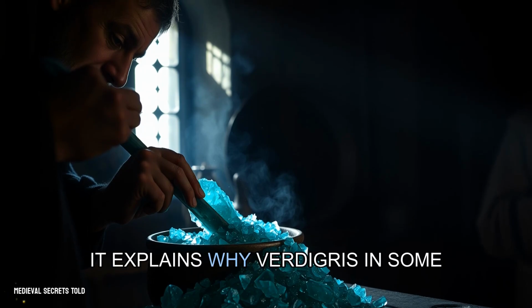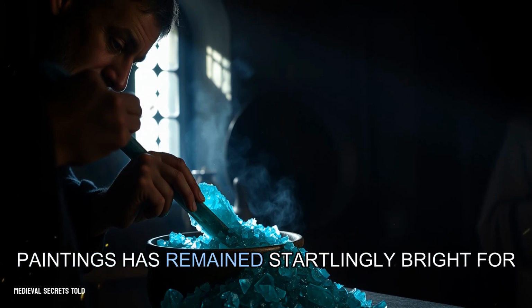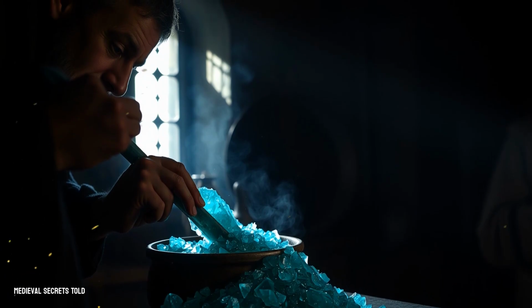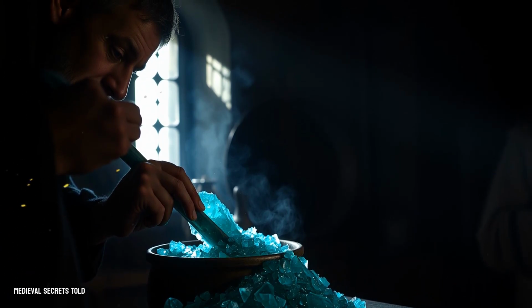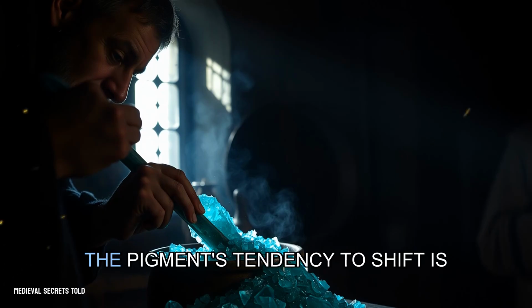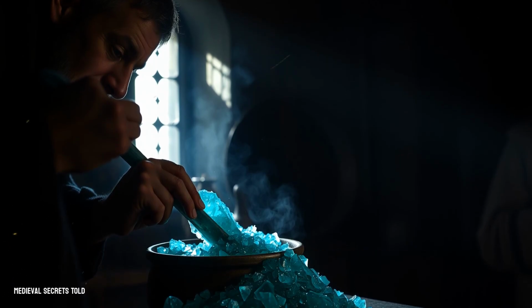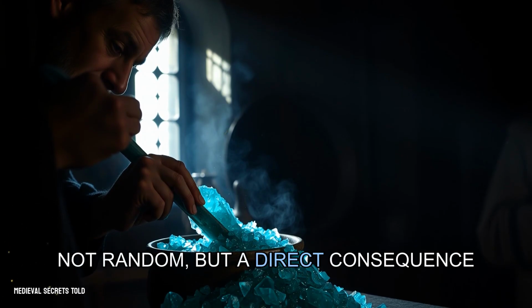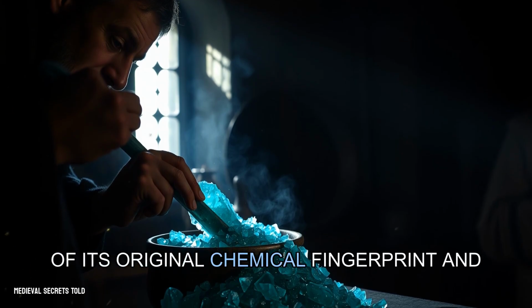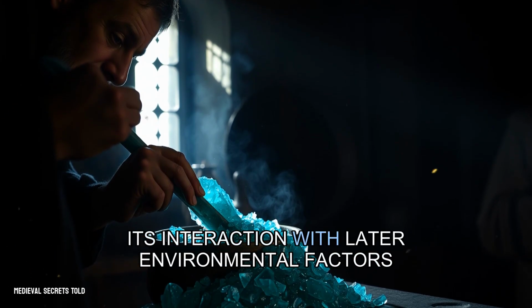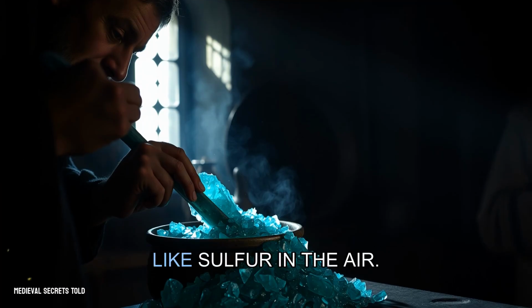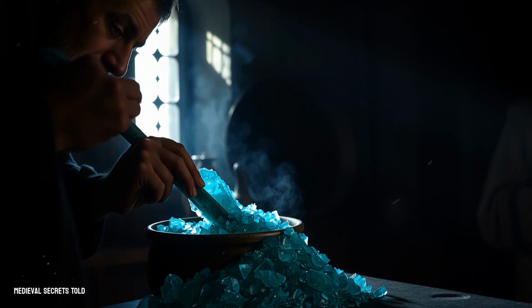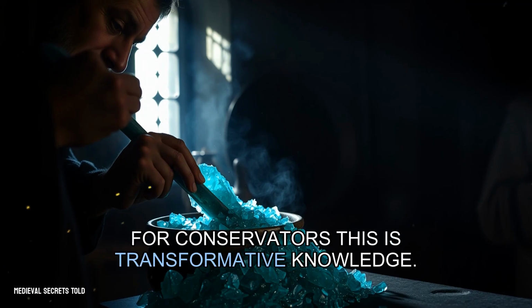It explains why verdigris in some paintings has remained startlingly bright for 800 years, while in others it has darkened dramatically. The pigment's tendency to shift is not random, but a direct consequence of its original chemical fingerprint and its interaction with later environmental factors like sulfur in the air. For conservators, this is transformative knowledge.